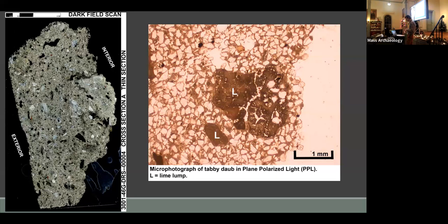And we can see this in thin section with underburned shell fragments, which also speaks to the inconsistencies in temperature during the lime burning process. Some planters preferred dead oyster shells over live oyster shells due to dead oyster shells being easier to collect and transport and containing less salt. Many advocates of tabby architecture emphasized the necessity of salt-free materials, believing the presence of salt resulted in a weaker material. Burning unclean live oyster shells also produces undesirable noxious fumes. So whether sourced from live oyster beds or ancient shell middens, it seems it was desirable to clean the shells of salt and organic material before the shells were burned.